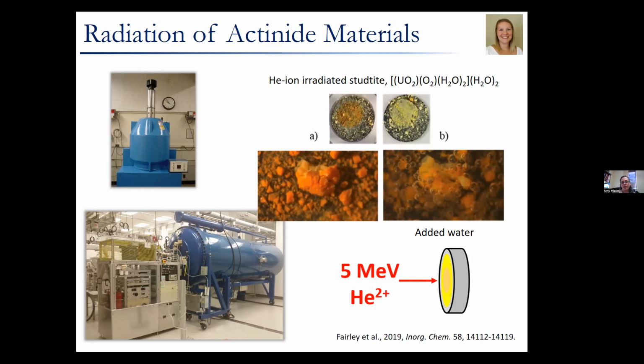The image on the left-hand side shows you can see exactly where the beam was, you can see the damage to the material. But then upon addition of water, we see a color change in the area that was irradiated. We see the formation of bubbles. And then we're able to determine that another amorphous peroxide, uranyl peroxide compound, formed.